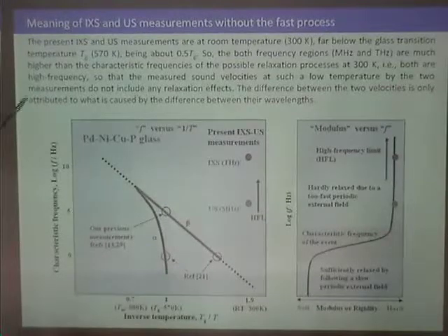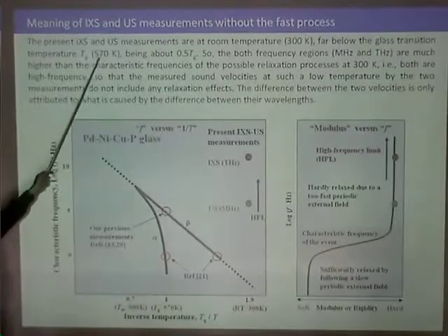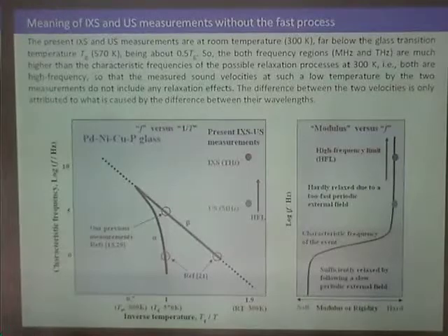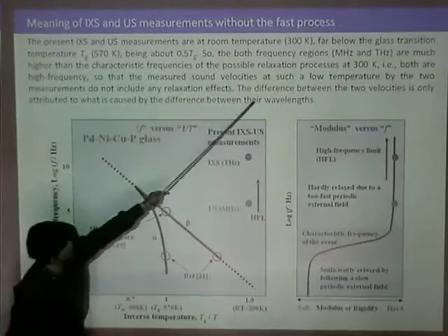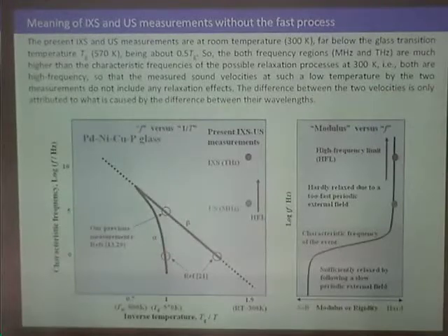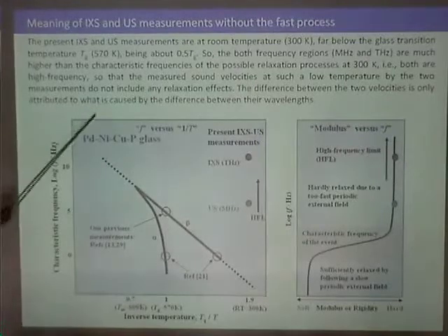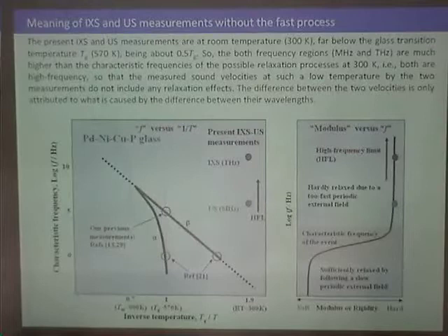The present IXS and US measurements are performed at room temperature, far below the glass transition temperature, TG. TG is in this case 570 Kelvin. So both frequency regions, megahertz and terahertz, are much higher than the characteristic frequencies of the possible relaxation processes at room temperature. Namely, the measured sound velocities from the two measurements don't include any relaxation effects. Therefore, the difference between the two velocities is caused only by the difference between their wavelengths.